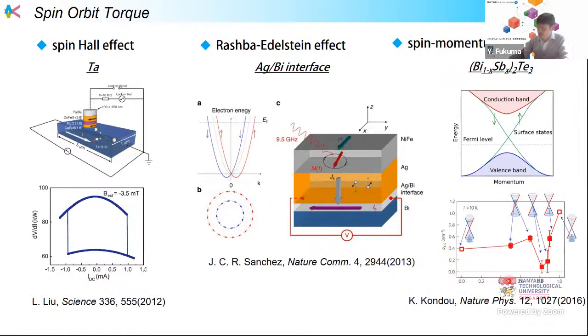For example, we can see this kind of charge to spin conversion effect as a function of the Fermi level. I mean, this is the case of the bismuth antimony telluride, but by changing the antimony, we can tune the Fermi level like this. Then, for example, at the Dirac state, upspin and downspin are degenerated. That's why the conversion efficiency will decrease like this. But, for example, in the valence band, we can get this kind of high value of the conversion efficiency from the charge current to spin current.